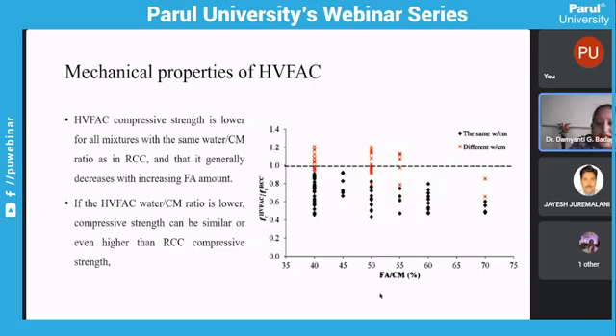Here are the mechanical properties. If a different water cement ratio or the same water cement ratio is used, what is the change? High volume fly ash concrete compressive strength is lower for all mixes at the same water cement ratio, and it generally decreases with increasing fly ash amount. If the high volume fly ash concrete water cement ratio is lower, the compressive strength can be similar or even improved. This is a universal truth: whenever we go for a high water cement ratio, we definitely have to compromise with the strength, and in concrete we can't compromise with strength. So we have to find an alternative solution.